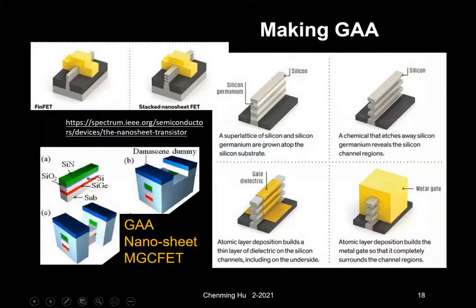Now, how do we make this nanosheet structure? Very briefly, it really has to do with growing the red sacrificial silicon germanium epi on silicon, and then growing the silicon channel, and you repeat it several times. Another red silicon germanium, another gray silicon. After you do that, you etch away the red and leave the silicon. And this is shown here. The silicon film is hanging. The red has been etched away. It's held up by the source drain, not shown here.